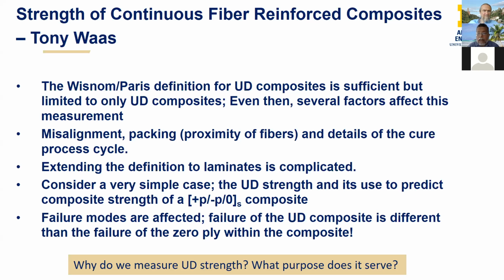Let's go to the lab and do the tests, right? Along the lines of what Federico mentioned, let's add also the fact that you can change the ply thickness. So now you have a very rich data set. Now here's the challenge. I only give you the strength value that I measure from the 0 ply. Can you now use that and predict all possible cases of the plus P, minus P, 0 symmetric composite test? Now, it's a challenge. If you do it, and some of us have done this, you will not be able to do it. If you only use the strength, and by the way, like Silvestre said, the strength is a distribution.